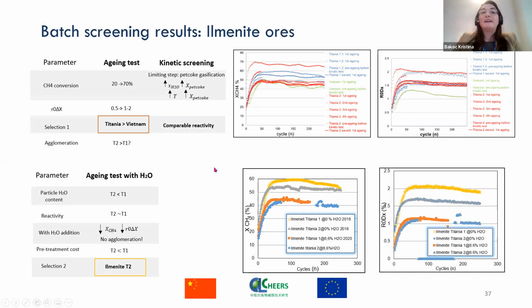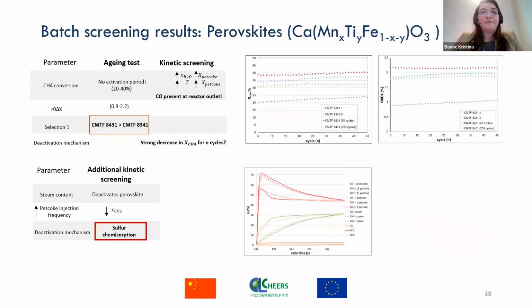So we decided to perform additional aging tests where different water contents would be added to the inlet fluidization gases. In this case, we desired to compare once again the performance of ilmenite T2 and ilmenite T1. What we found was that upon addition of water, there were no longer agglomeration issues with ilmenite T2. And since overall pre-sieving and pre-treatment is significantly cheaper for ilmenite T2, we would say that overall reactivity is high enough that we can suggest ilmenite T2 for further tests.